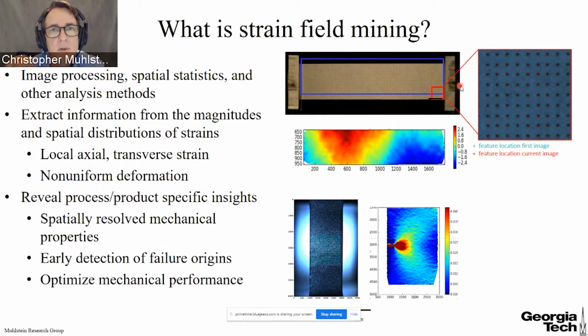We can do this with specific features, and we can even do it with just the native piece of paper that's plain, because there's enough contrast that we can see visually. And by tracking the motion of these different features on the surfaces, we can extract information that tells us what the local motion of the paper is doing, what the local mechanical properties are.